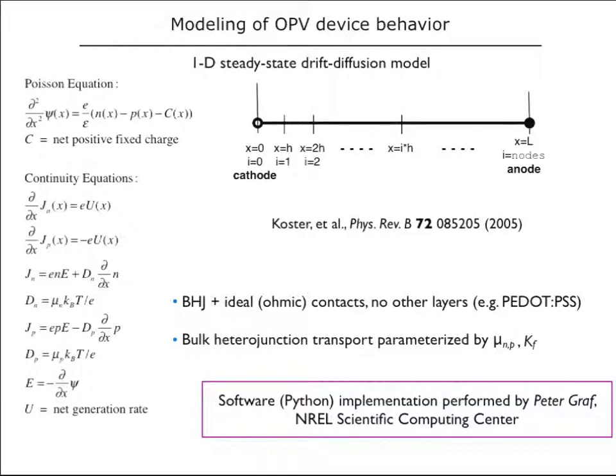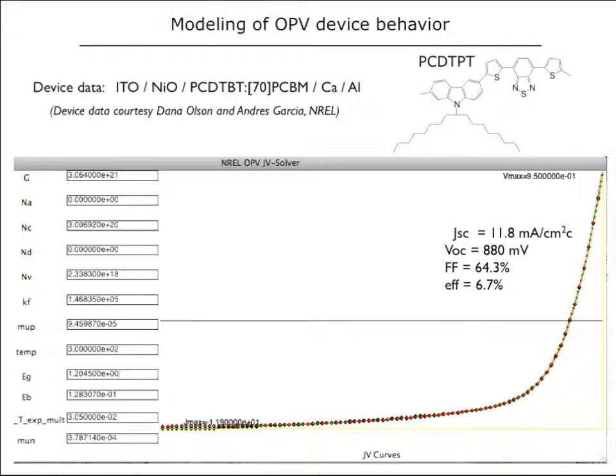So we can incorporate that into a full device model to analyze the JV curves. I won't bore you with the details, but these are more or less standard device equations you would find out of, for instance, Sze's book on semiconductor physics. We're solving Poisson's equation and the continuity equation. And we're doing this in one dimension and just solving this numerically. This is an ongoing project that we're doing with Peter Graf at NREL in the Scientific Computing Center. And what we can do with this in the end is fit a JV curve. This is some data from NREL, given to us by Dana Olson and Andres Garcia. This is about a 7% device from this material, PCDTBT. So what we have is a whole range of inputs: charge generation rates, density of states, recombination rates, mobilities, temperatures, and so on. And through careful fitting of the data to both experiment of the individual quantities and the JV curve, we can get a reasonable idea of what the device physics is.